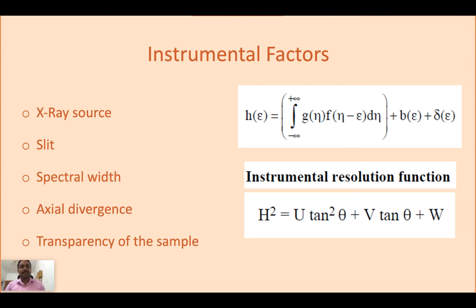Then only if your sample is nano, your broadened peak is related to your nano material. Otherwise, the broadening is happening due to the instrument. Please be careful with these aspects. So your instrument also will contribute to your data. You should be very careful with that. Not always is the sample going to contribute. The instrument resolution function will vary with all the instruments, and the operators have to run the standard data given with the instrument, calibrate the instrument, and also calibrate that particular instrumental broadening. That will be contributing to your sample also. So better you negate that instrumental broadening and talk about your sample broadening, which may be due to your nano sized sample.